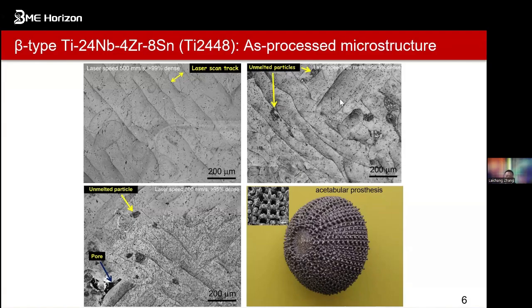Therefore, it may be concluded that the laser energy density was not sufficient to completely melt all of the powder particles. In the samples with the lowest density, the number of unmelted particles has increased, and porosity is clearly present in this kind of part. They also produced an example of an acetabular prosthesis by selective laser melting at a laser power of 200 watts and a laser speed of 550 millimeters per second, because they can get nearly fully dense parts, so you can see the parts.